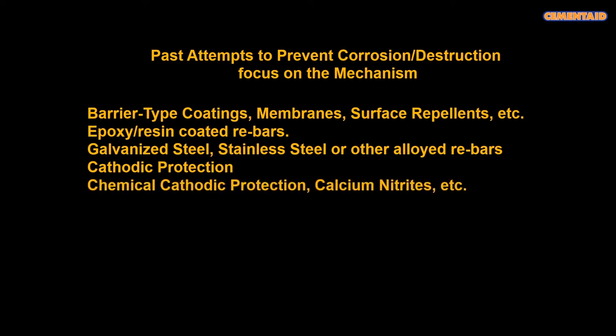Another way is to use chemical cathodic protection. Things like calcium nitrites can be mixed in with concrete. And what they do is basically they will absorb chlorides and form a material which is non-destructive. The problem with these is you need to calculate the depth of potential chloride ingress over a period of time and put sufficient of these different additives into the concrete to last for the projected life of the structure. It's quite a difficult process.